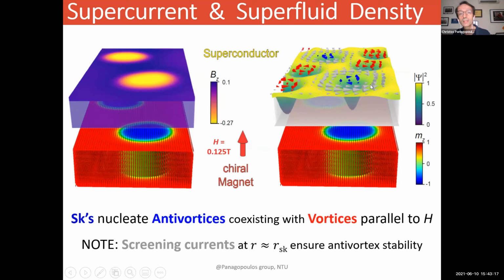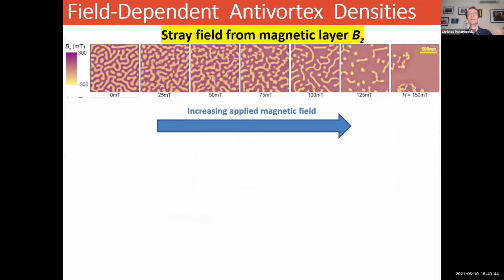Now, note that the gray screening currents, which are at a distance or a radius approximately the radius of your magnetic skyrmion inside the multilayer, are the ones that ensure anti-vortex stability. So you can immediately see the formation of skyrmion anti-vortex pairs, and they're actually connected energetically, just as we anticipated through the connection. And you can do more.